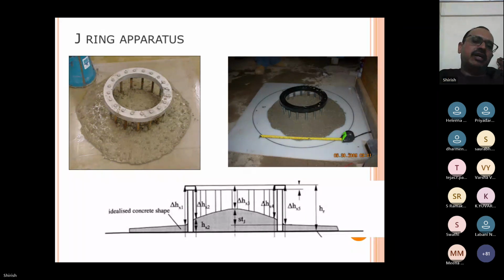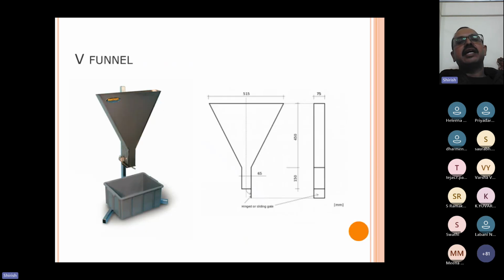As you can see in the third figure at the bottom, at the center the height is very high, that clearly indicates that segregation is there. So what is the specification? The difference between the height outside the J-ring and inside the J-ring should not be more than 10 mm. That is what we have to see. If the difference is more, it will show that the segregating ability is still there.